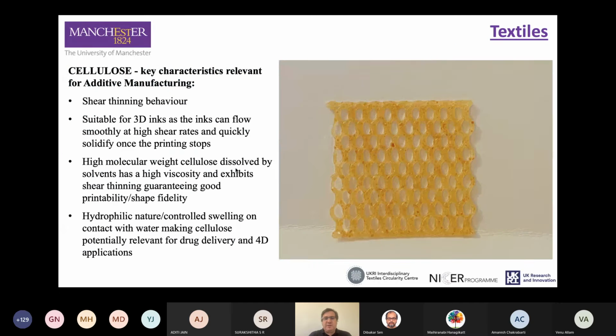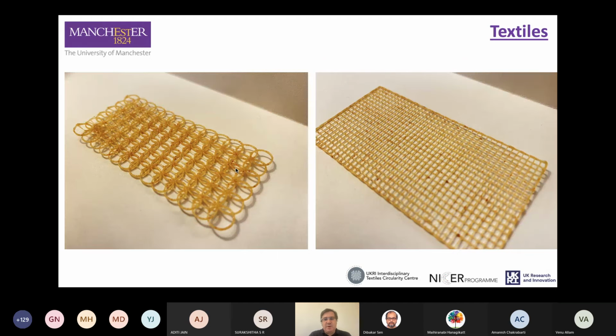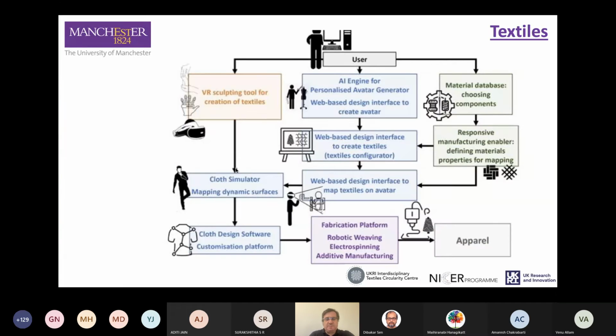We started with the first approach, so we started using extrusion-based machines to extrude the bacterial cellulose together with PLA and PCL. Despite the good properties of cellulose, such as the shear thinning behavior, which makes the printing process easier, it was not possible to incorporate more than 30-35% of bacterial cellulose in our structures. So that's why we are now focusing on the ink approach. But here are some of the preliminary structures that we produced.